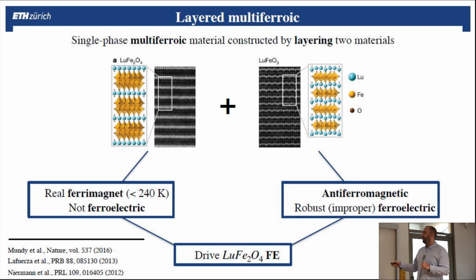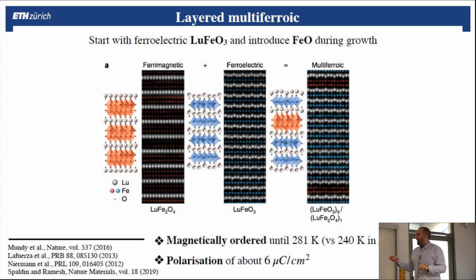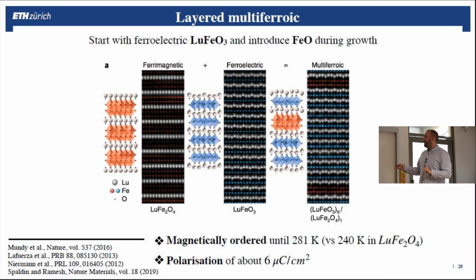And the idea is that they are not so far away. You can see from the chemical formula that they look similar. And the idea is to stack them together and see if one can transform this material that has a magnetization to also have ferroelectricity. So that was done by starting the growth with the lutetium ferrite and then introducing iron oxygen in a controlled way.